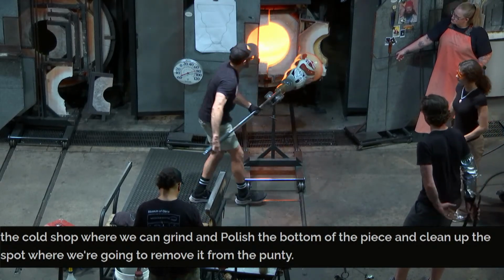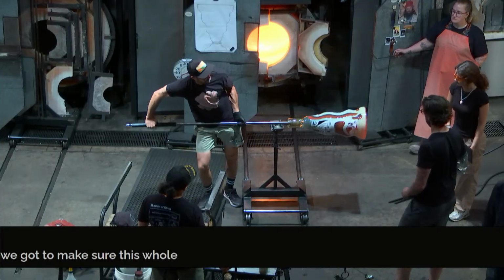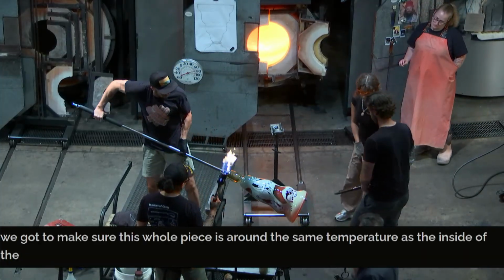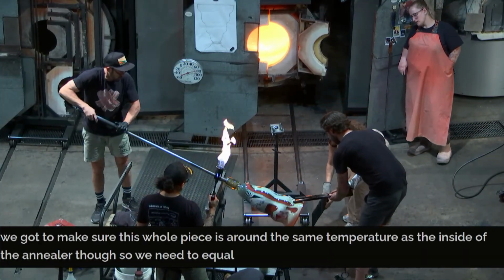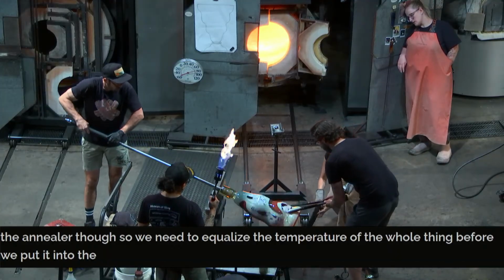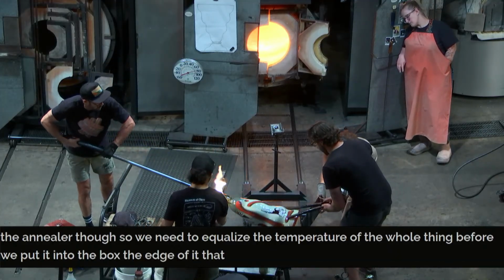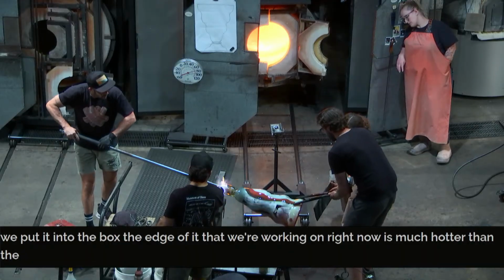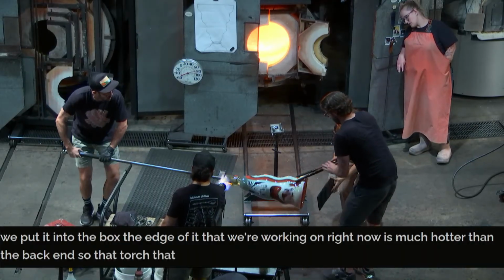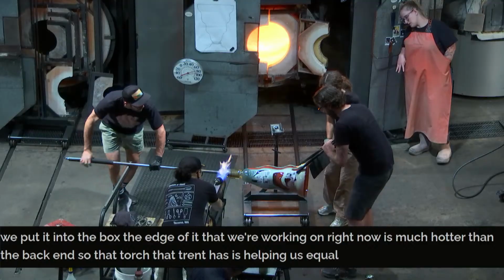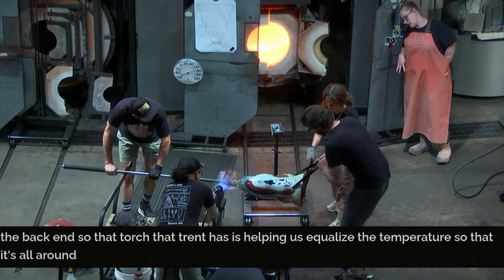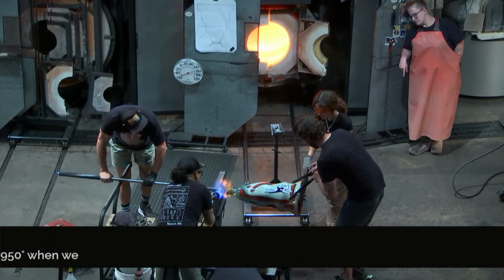We got to make sure this whole piece is around the same temperature as the inside of the annealer though. So we need to equalize the temperature of the whole thing before we put it into the box. The edge of it that we're working on right now is much hotter than the back end. So that torch that Trent has is helping us equalize the temperature so that it's all around the same 950 degrees when we put it into the annealer.